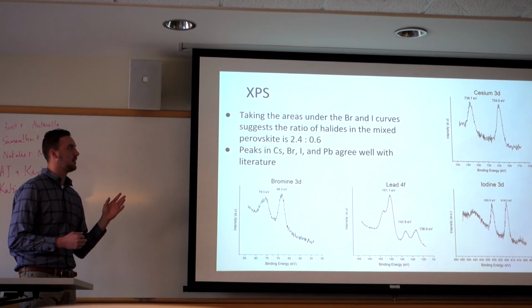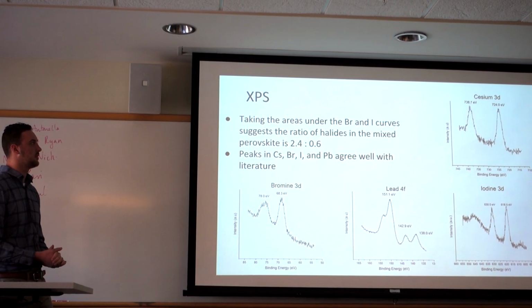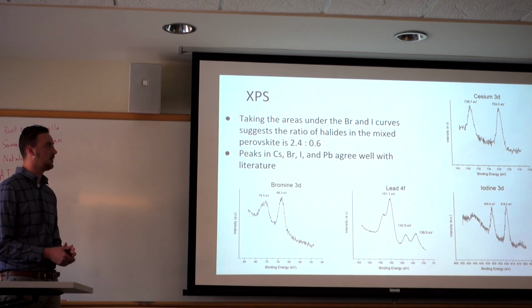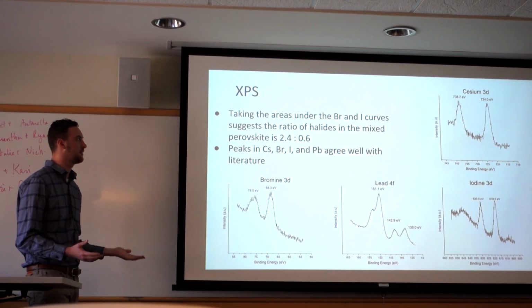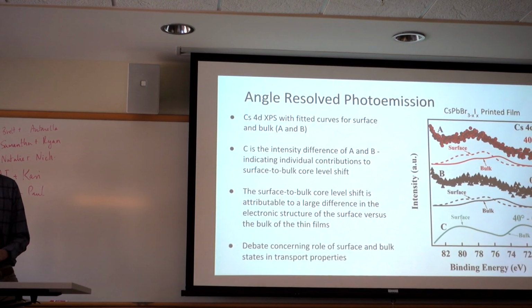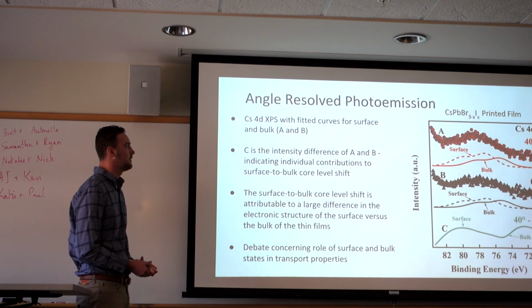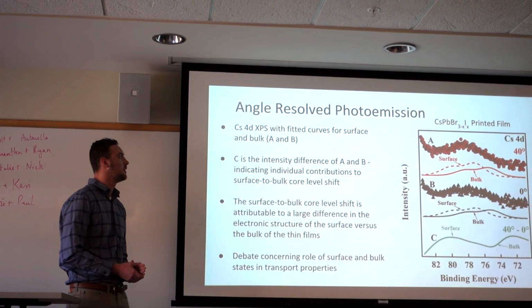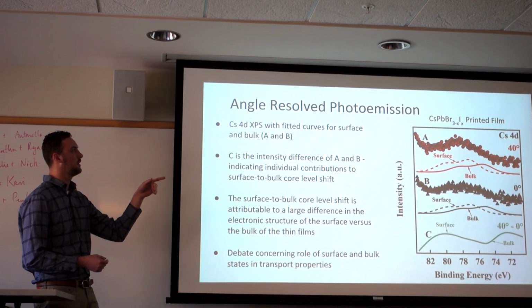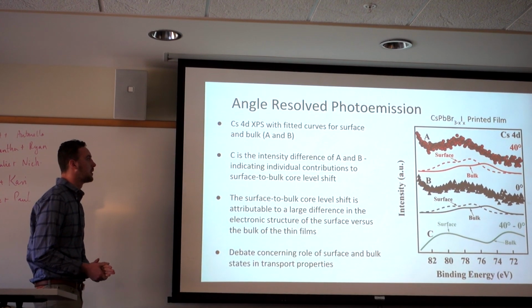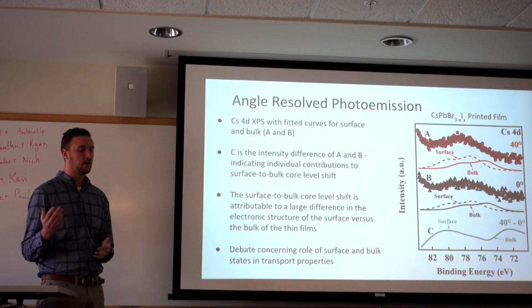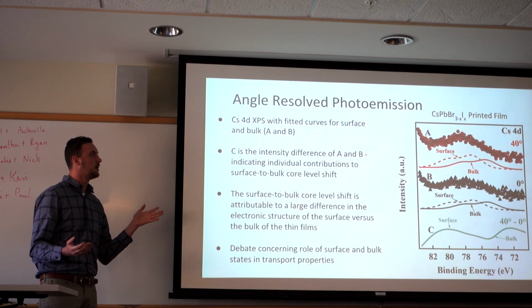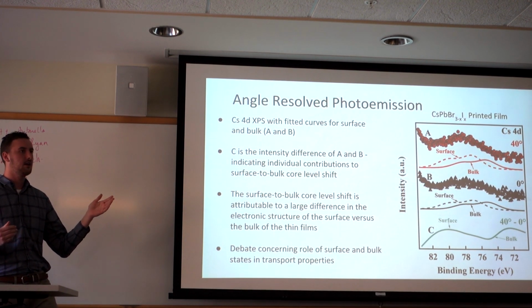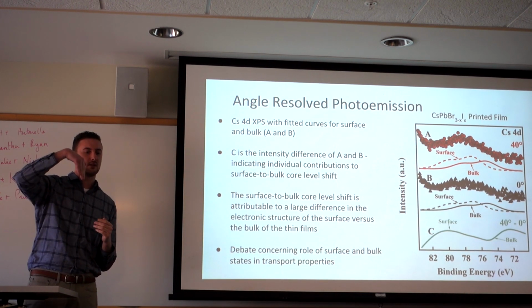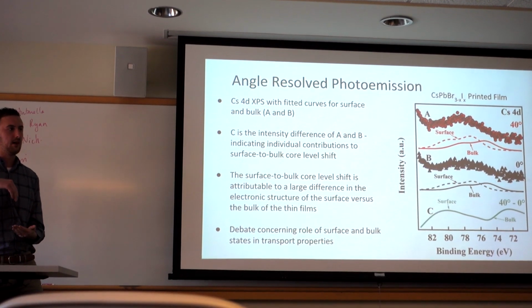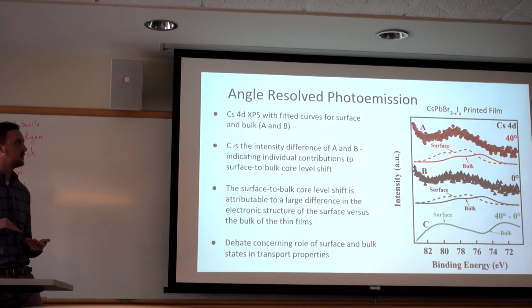And the reason they're weird decimals is because we want the total to combine to 3, which is the amount of halides in the chemical formulas for these perovskites. And then we noticed there was a core level shift between the surface and the bulk of our material in the cesium 4d spectrum. So we decided to use angle-resolved photoemission, which is the exact same experiment as the previous slide, except now we take a photoemission at 0 degrees with respect to the normal, and then at 40 degrees with respect to the normal.